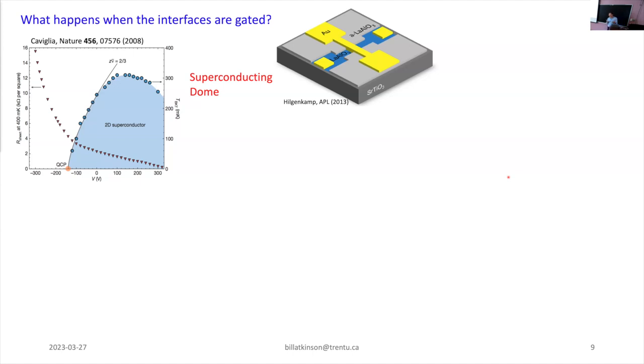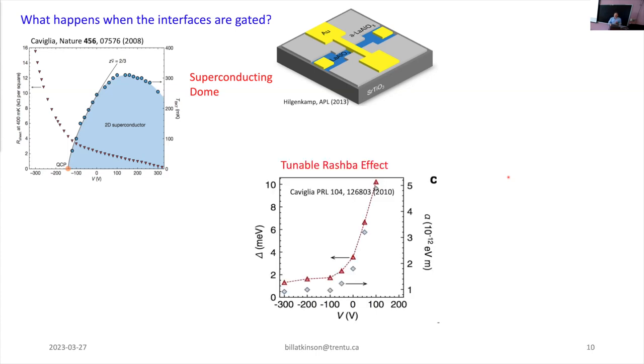And because of high temperature superconductivity, everybody gets excited when they see a superconducting dome, because it must be that something interesting is happening. And in fact, it is kind of interesting that the transition temperature would go down again as you increase the electron density. That's not what BCS theory would tell you. This actually has sparked an enormous debate and reinvestigation of mechanisms of superconductivity in strontium titanate that's still going on today. And in the last couple of years, I would say there are some very interesting and compelling mechanisms for superconductivity involving things like Rashba phonons that I find fascinating. I don't know what the answer is to why this thing is superconducting, but there's a lot of really interesting ideas coming out about this. A later set of experiments showed that there is a tunable Rashba effect.